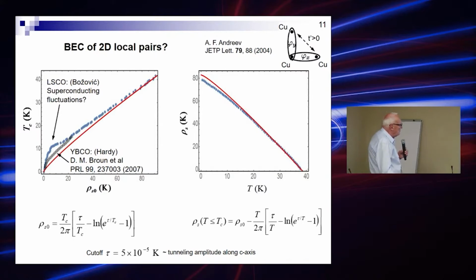Even better, this is temperature dependence of the superfluid density, and of course we cannot take 2D ideal perfect Bose case because TC is 0, but we take some cutoff tau, which means that we have some along c-axis some three-dimensional motion, but very, very small. You see that tau, which fit these experimental results, is 5 multiplied by 10 to the minus 5 Kelvin. It's very, very small.